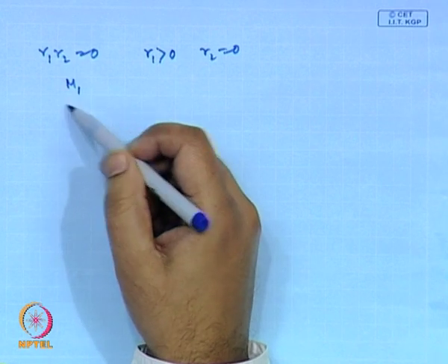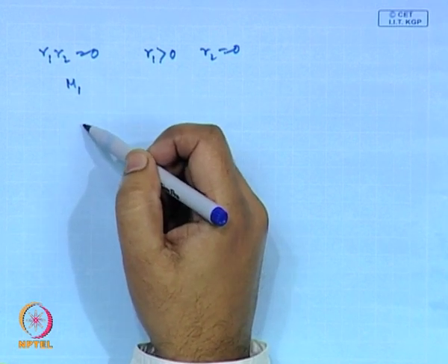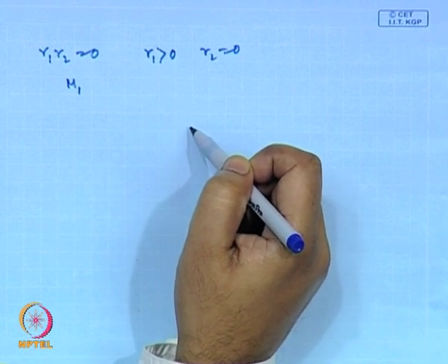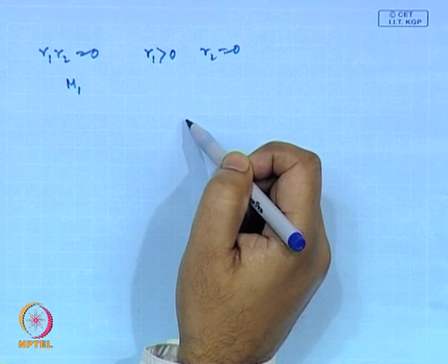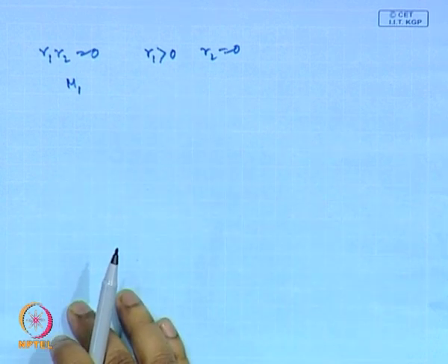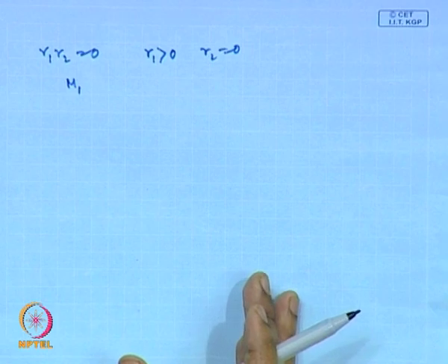If you start with excess M1, then at the beginning you will get alternate copolymers, and when all the M2 is getting incorporated in the copolymer chain, the rest of the M1, which is remaining, will homopolymerize. So you get an alternate copolymer at the beginning, and at the end you get a homopolymer of M1.